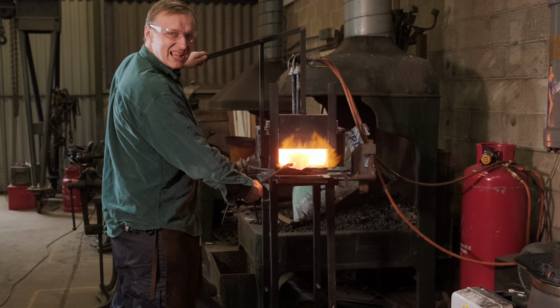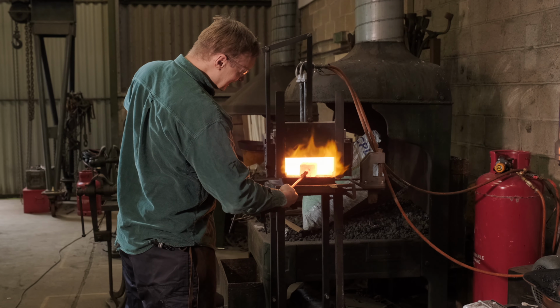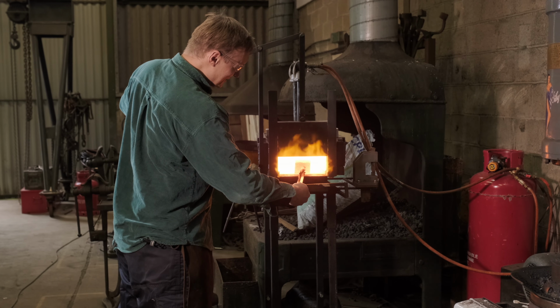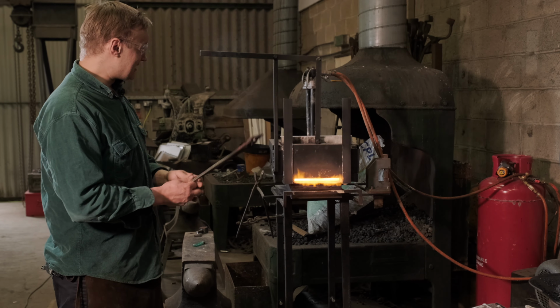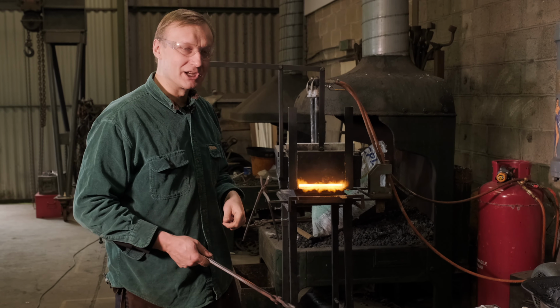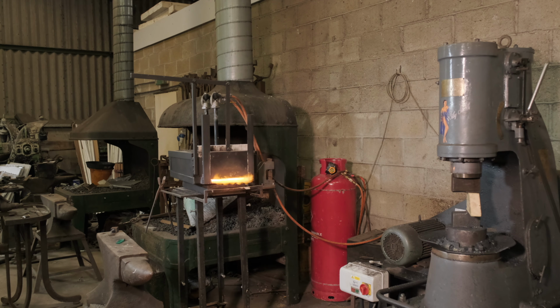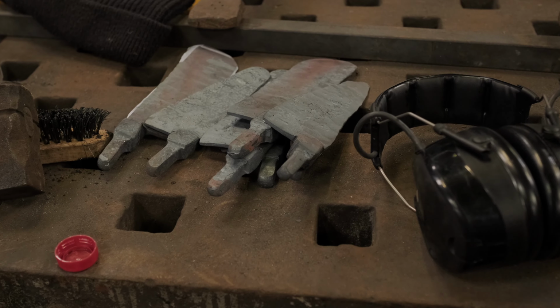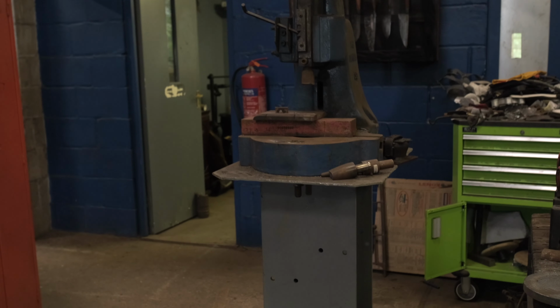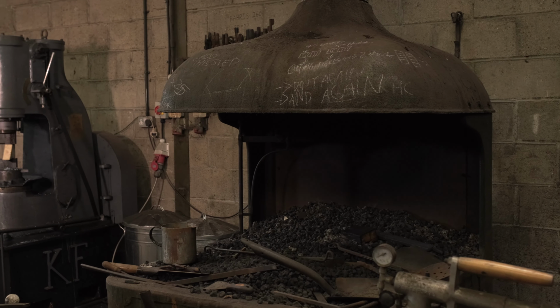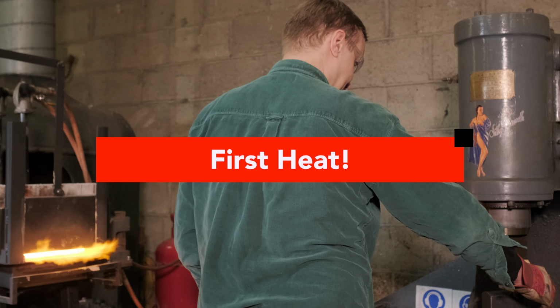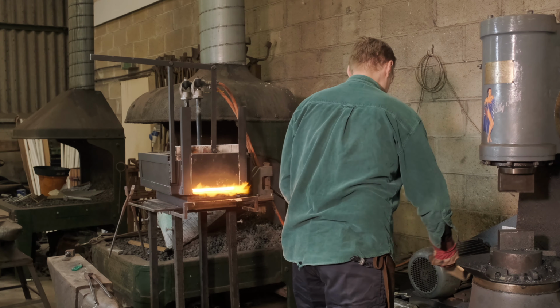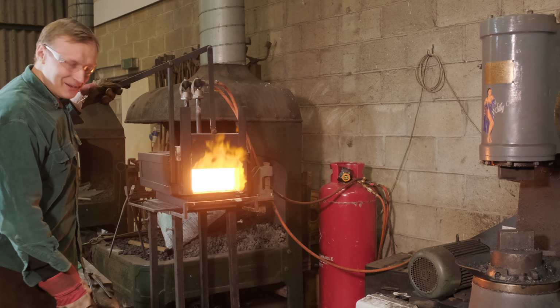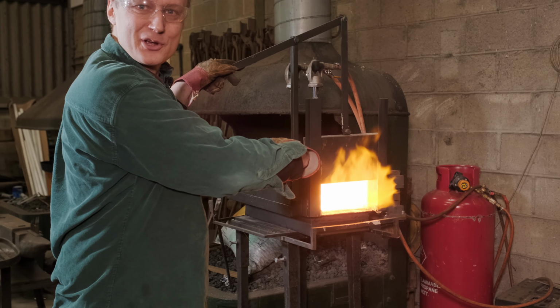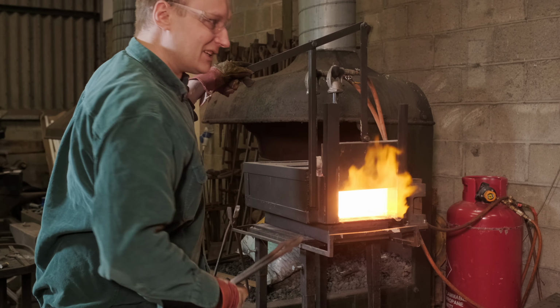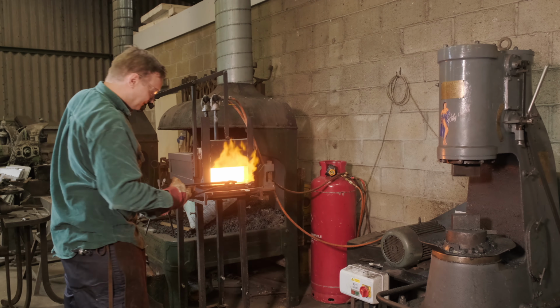Alright, so it is getting nice and hot in here. The stack is pretty much the same color, but I'm gonna leave it in there for another couple minutes just to make sure that the temperature is the same through the whole stack before we actually start forging it. So the stack now is pretty much the same color as the inside of the forge. So that would mean that we are at about 1000 degrees.